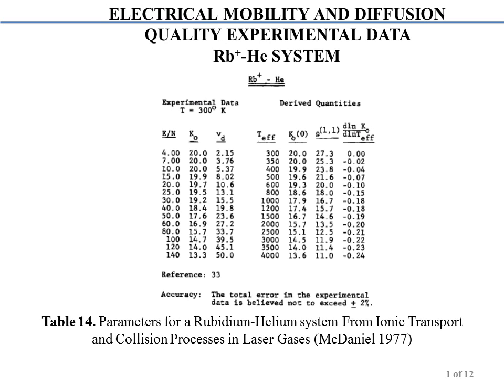So therefore, for rubidium ion, terminal velocity is 8.02 times 10 to the 4 centimeter per second in helium. We can then estimate, as we will do later, the diffusion of the rubidium ion through selected thin film oxides in centimeter squared per second by use of the electrical mobility equation.